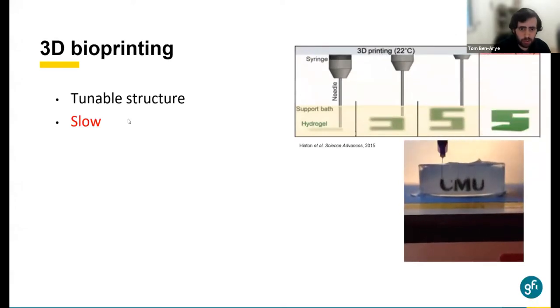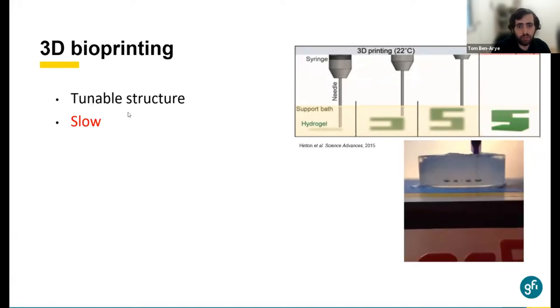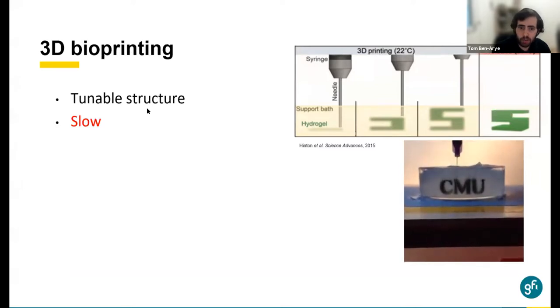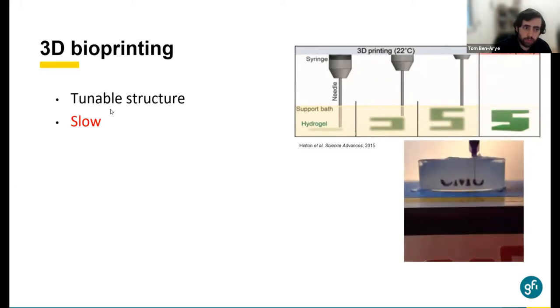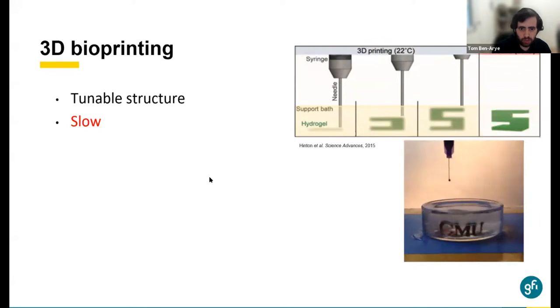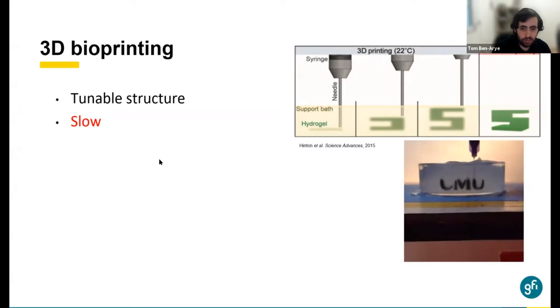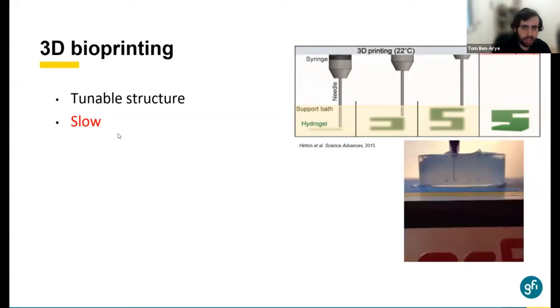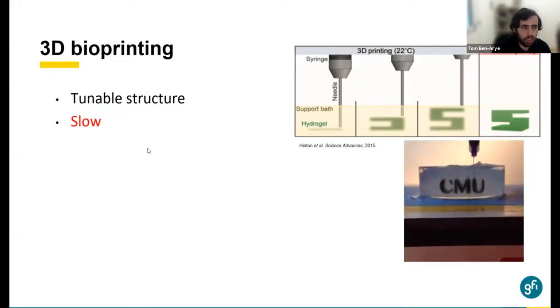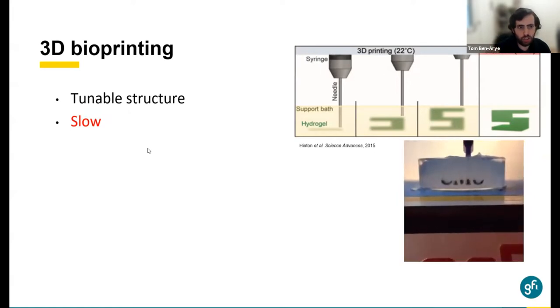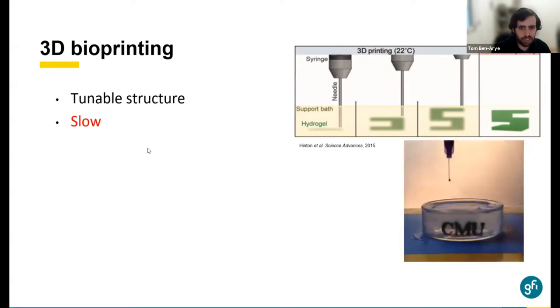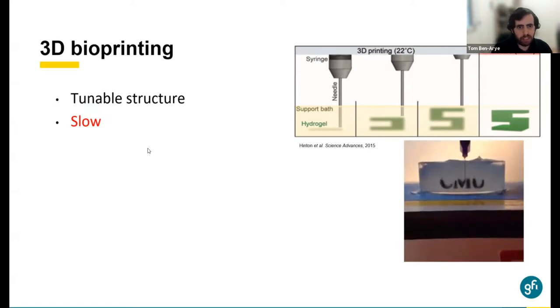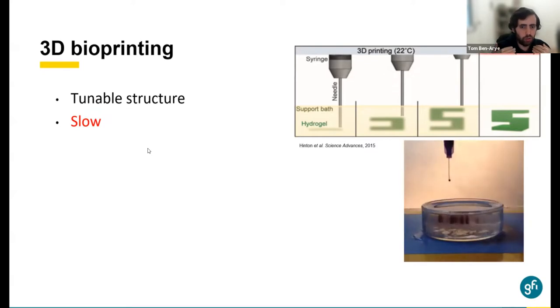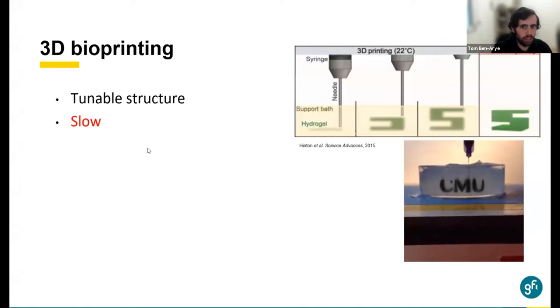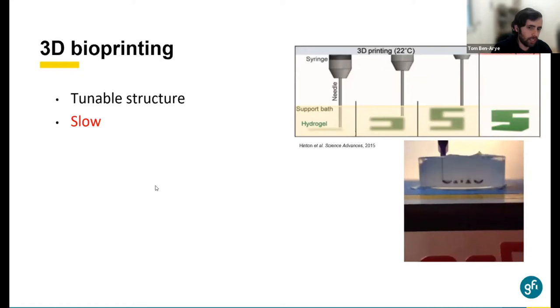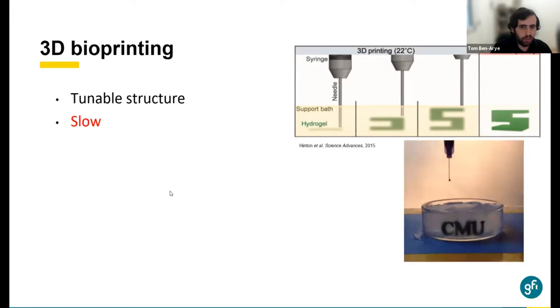3D printing, I won't discuss it because you all know it. I'll just mention that it is very favorable in terms of the tunable structure, it can generate any structure that you are interested in, with good resolution. However, the very large issue with 3D bioprinting is that it is one of the slowest ways that you can use in order to produce anything. Perhaps there will be advances in the future that will make it more scalable, but currently that's a big issue, especially when we think about cell culture. You have adherent cells, you need to trypsinize them, you need to harvest them and put them in this solution that you want to 3D print, and you cannot hold them in this solution for a very long time. Cells will not behave normally that way. So that's still an issue. However, there are merits because you can really fine tune your samples using that.